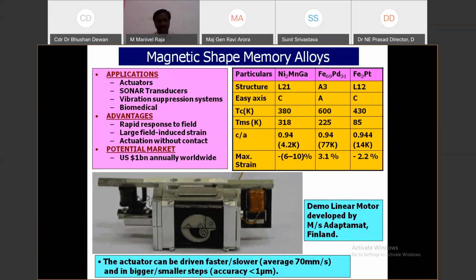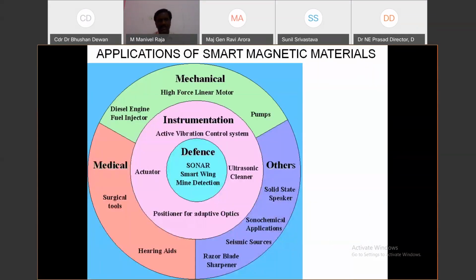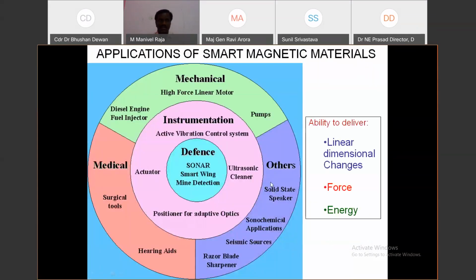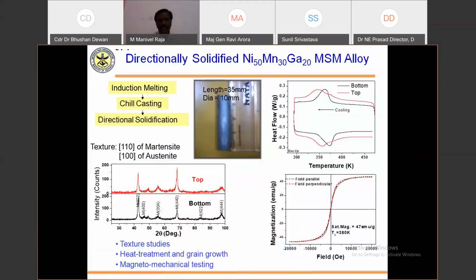DMRL has just started on this material. This material also has similar applications to magnetostrictive material. It can be used for sonar, actuators, and sensors. At DMRL, we are using the same processing technique, directional solidification, which is used for the magnetostrictive material. The material system that we have developed at DMRL is again a nickel-based alloy. It's nickel, manganese, and gallium, a ternary alloy.